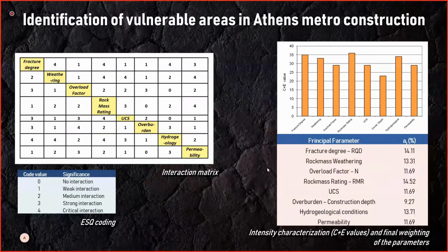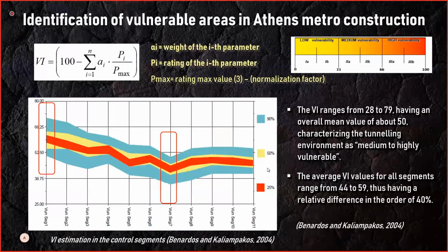You can see that 4 are the more dominant parameters: the fracturing degree, weathering, rock mass rating, and hydrological conditions. The final vulnerability index is given in this slide, where the rating of each parameter is multiplied by the weighting of the respective parameter at a scale from 0 to 100, with 100 being the most adverse and most vulnerable condition. You can see that the best conditions are found in segment number 7, which has a central value of around 40 and an upper limit value of around 60. Accordingly, we can see that the segments presenting the greatest vulnerability are segments 1 and 2, having central values around 60 and upper values of around 70.